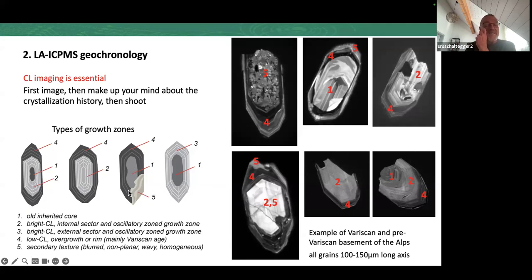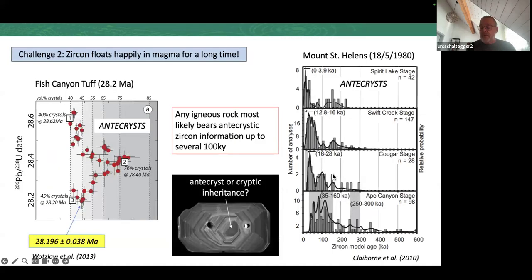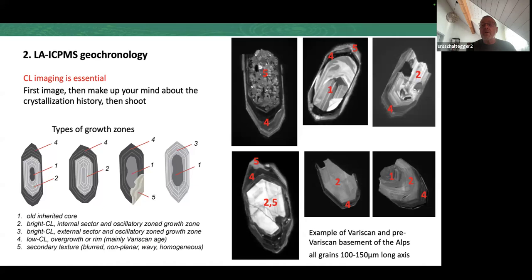And 5 would be any sign of any overprint, blurring, non-planar, planar, wavy zones. So this is, for instance, a core or a growth zone 2 actually rather, which is completely altered by secondary effects. Here we see this secondary rim. Here we see also probably a recrystallized rim. And only then target these zones separately, and then establish your set of analyses from the zone 2, and then only calculate the age from those analyses which are in the same zone.